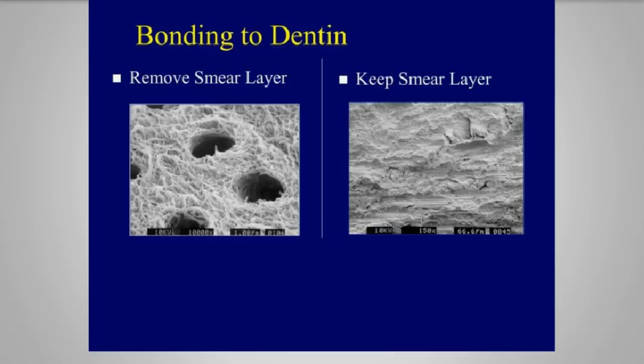So if you look at the bonding to dentin, either we're going to remove the smear layer and open up the dentinal tubules, 10 to 30,000 per square millimeter, which also invites hydraulic flow from the odontoblastic processes and could translate into Brännström's theory. Or we're going to keep the smear layer intact and collapse it and form our micromechanical retention that way. One is total etch and the other is self-etch.